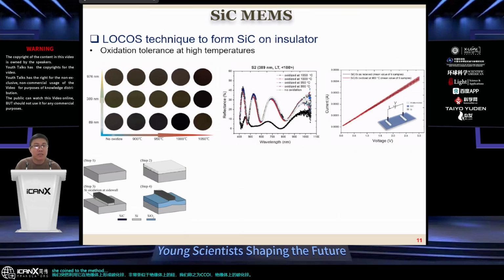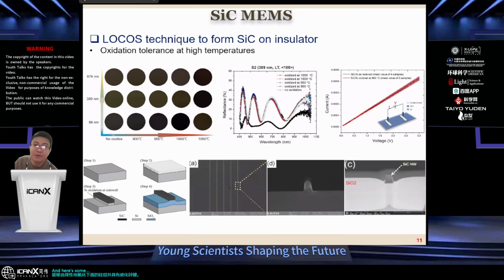So the method that we form silicon carbide on insulator is we grow silicon carbide. We start with a silicon wafer, we grow silicon carbide on silicon, and then we use e-beam lithography to make silicon carbide nanowire, in green color here, and expose the silicon a bit. After that, you can oxidize at 900 or 950 degrees C, where silicon will be oxidized, and silicon carbide is not attacked. By doing so, you will be able to selectively oxidize the silicon layer underneath and have silicon carbide on oxide layer. And here's some SEM images that demonstrate the concept to form SiCoI.